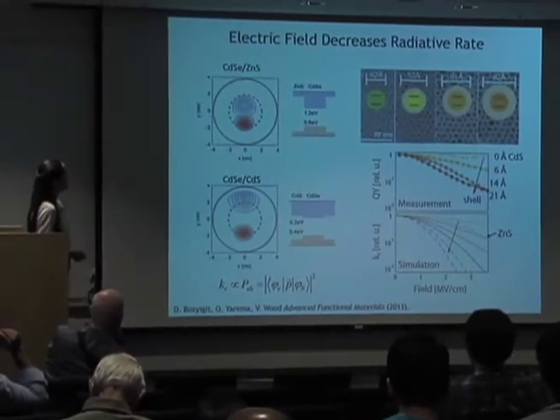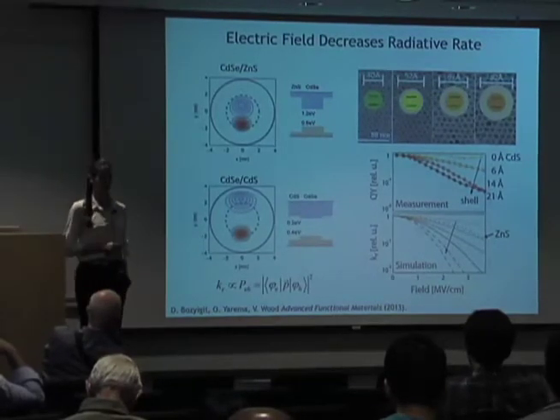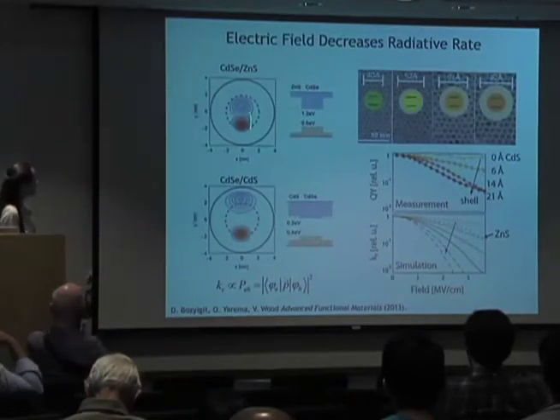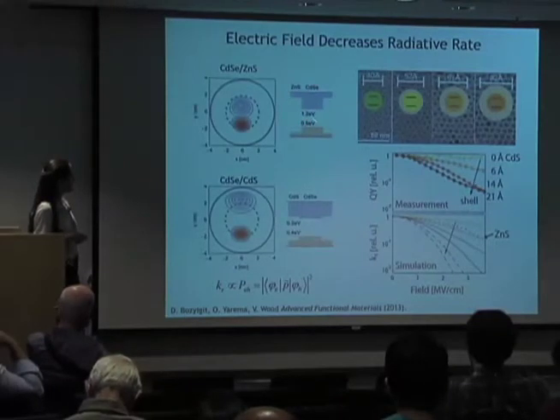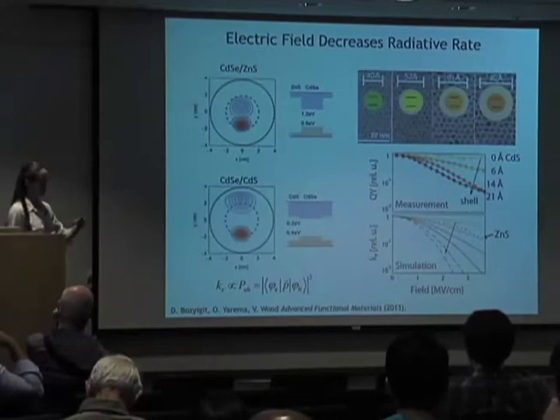We did tight binding simulations to look at the effect of field on our optical matrix element, which can be related to the radiative rate. And what you see here is plotted in real space. What's inside the dashed lines is the core material, and this outer region then is the entire quantum dot, so core and shell. And in one of these structures where you have the electron and hole tightly confined by the shell, when you apply an electric field, you get spatial separation of your electron and hole wave functions, but they don't